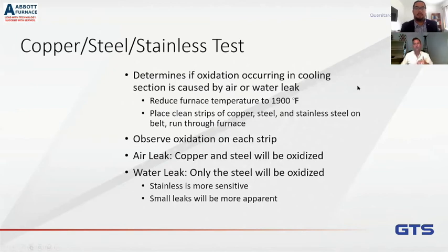So the first thing you want to do is reduce the furnace temperature to 1900 degrees Fahrenheit. That's because you want to be below the melting point of copper. So you take your highest temperature zones and just lower them below the melting point of the copper. Then you're going to take a piece of copper. It could be a piece of pipe. It could be a shim that you've bought. It can be anything.